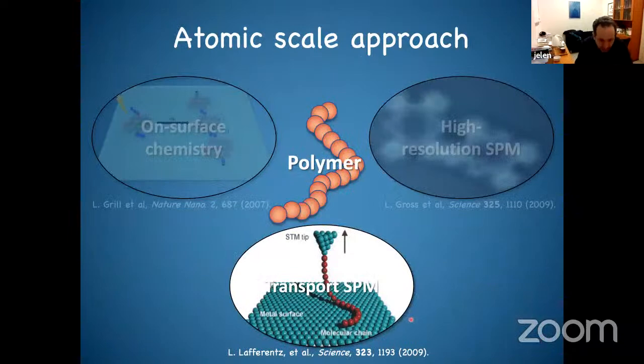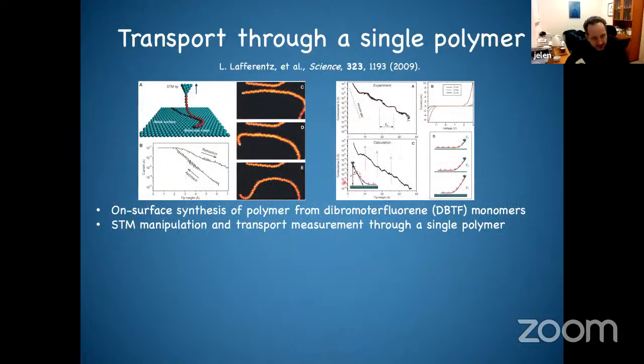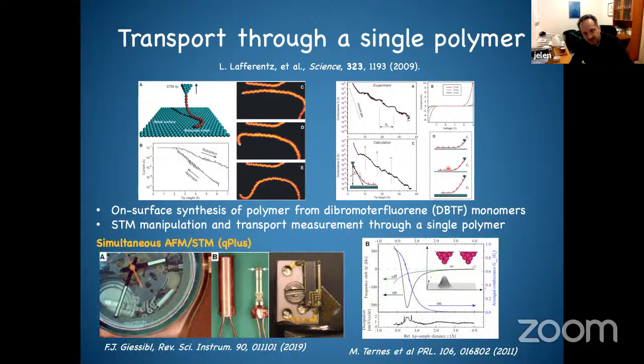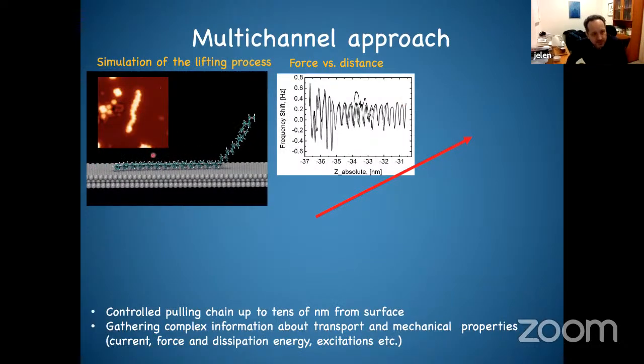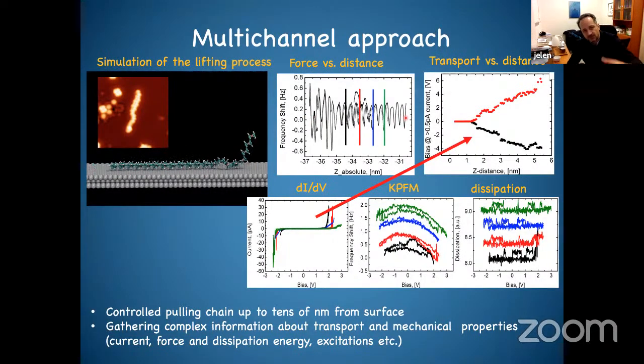Finally, I'm not going to discuss this today, but when you grow these chains on the surface, you can pick them up from the surface and measure the current. This was done in the group of Leonard Grill. These days, when you combine it with AFM and STM, you can also measure current and mechanical response simultaneously. Here is recent work we have done growing organometallic chains made of ferrocene. This is a simulation of what happens when you pull the system out, and this is the mechanical response you measure. From that, you can also measure the transport properties and so on. But I'm not going to discuss this today.